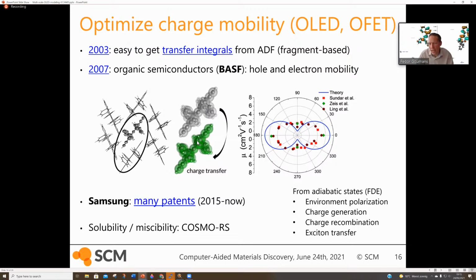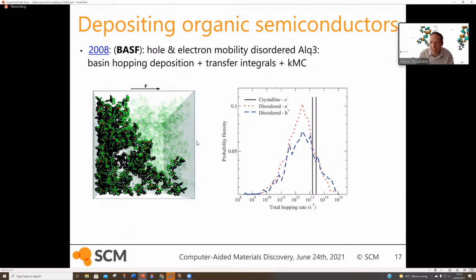And as you can see, here, for instance, the hopping rate in a crystalline material is typically much larger than it is in a disordered material, and there's typically a spread of different mobilities. But as you can see, the peak of the Gaussian is not exactly at the height of the mobility you would get in an ideal crystalline material. So it's good to know a little bit what the morphology does to your charge mobility, but also to other properties like exciton binding, exciton coupling, and emission properties.